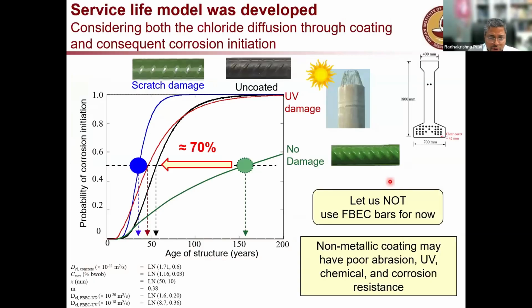Okay. So what we found quantitatively is that if there is no damage on this bar, a very perfect, pristine epoxy coated bar, then you will get a very long service life, 150 years in one case. But unfortunately, most of the structures get exposed to scenarios like this. So this is an epoxy coated bar exposed to sunlight. Definitely you will have cracks on the coating.